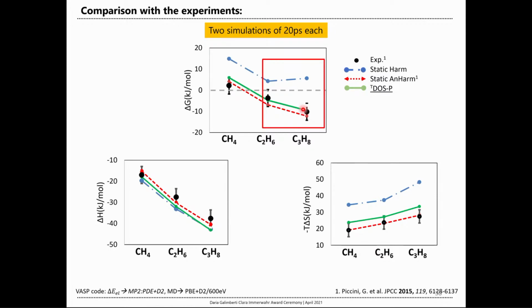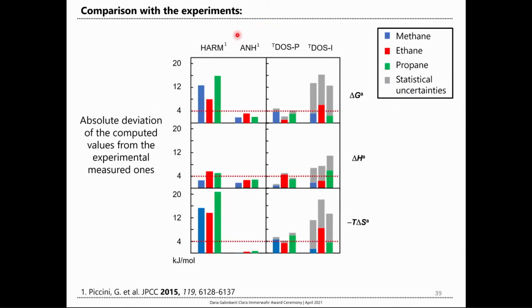And before I said to you that we cannot really use directly the vibrational density of states because there are also other contributions, and we need this projection procedure. And now I want to show you why. In this plot, what I have is the absolute deviation of the computed values from the experimental ones, for methane, ethane, and propane. Here, this gray shadow is the statistical uncertainty for my 2 picosecond trajectories. And this one is when I use my projection procedure. In this one, it is if I don't project my vibrational density of states. And as you can see, the simple projection of exactly the same two trajectories reduces the statistical uncertainties from 10 kilojoules per mole to only 1. So you can see that it's really this projection and filtering procedure that makes things work.